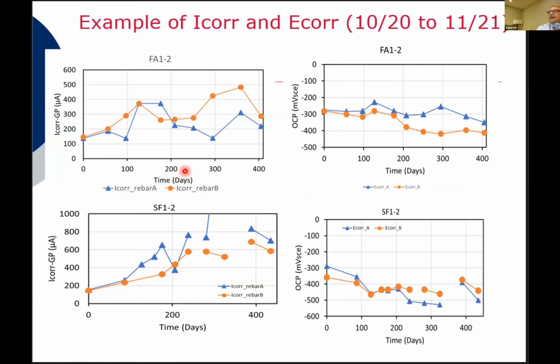Here are some of the results from the monitoring using the galvanostatic pulse for a couple of samples. On the left is one that contained 20% fly ash, and you can see that the magnitude of the current was larger than 100 microamps over the whole period, and reached situations where it was up to 500. And the corresponding potential, these values are versus calomel. If you would like to have these versus copper sulfate, you need to shift them 70 millivolts more negative. And here, there is one that contains silica fume.